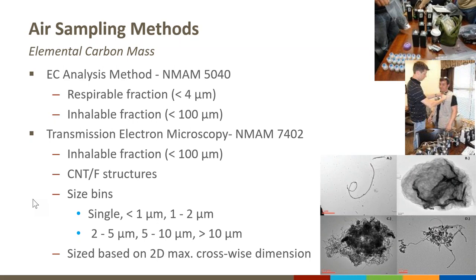A transmission electron microscopy sample was also collected with each personal breathing zone set of samples. The analysis method was NIOSH method 7402, which was originally designed for asbestos. Each sample was collected at the inhalable size fraction. And since the method was designed for asbestos, we had to alter it slightly to make it more specific for carbon nanotubes and nanofibers. What we refer to these as are carbon nanotube and nanofiber structures.